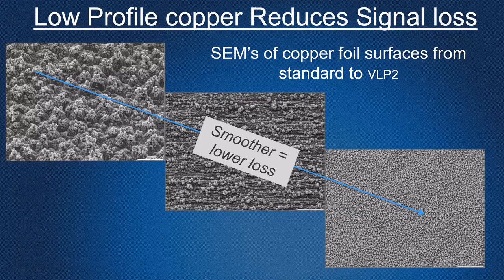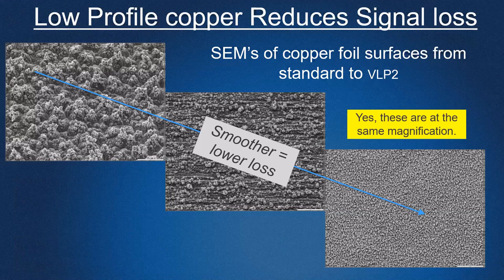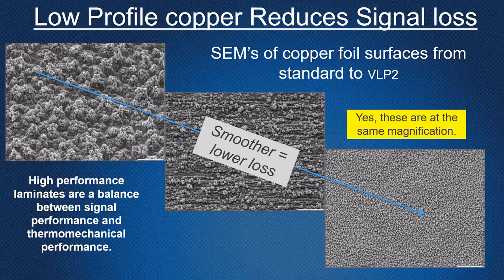I did want to show this slide though. These are all at the same magnification. These are just different SEMs of copper foil, and you can see how the topography changes quite a bit. Wow. And obviously, for higher performance, higher speed circuitry, you're better off with the lower profile copper. Now, you will have lower peels, so using that on a surface where you have components needs to be considered. Whereas if it's an internal layer, it's probably not a big issue, but copper foil profile is very important.